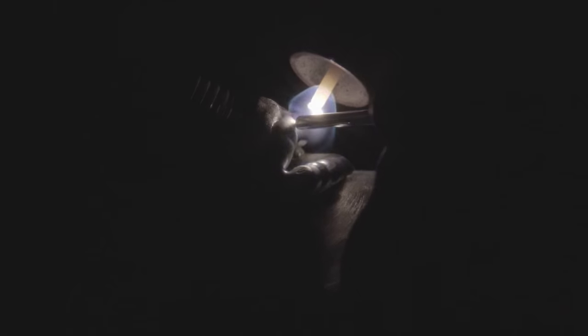I will say that I did step up to 3/32nd or 2.4mm wire, which is actually not a great idea in this case. The problem with using larger filler is you need more amps to melt it, and that makes it a little bit harder to control your deposition rate, or how much wire actually melts into the pool. It tends to make the final bead look a little bit bulky or clumpy, which is not usually the desired look for this kind of thing. Ideally you want every single bead to look nice and smooth and flowy, but sometimes you make dumb decisions like this, and at the end of the day, I really just should have stuck with 1/16th wire. You'll see exactly what this looks like in just a couple of minutes.